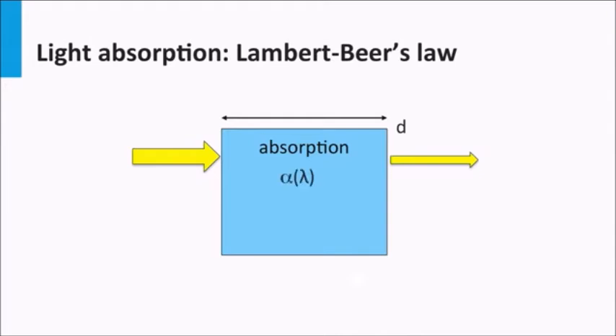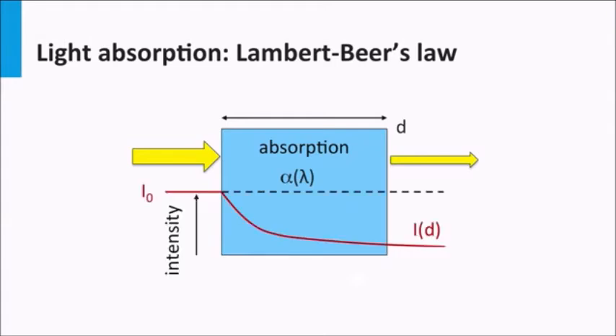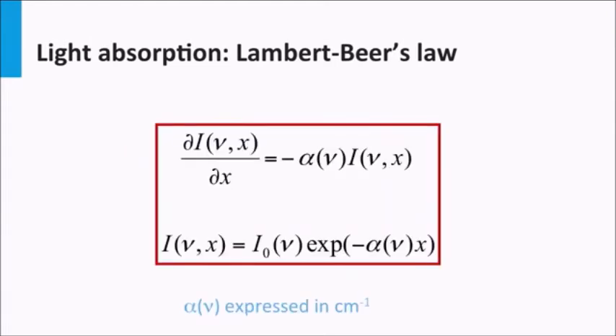The absorption of a medium can be defined in terms of an absorption coefficient alpha. The dimension of the absorption coefficient is 1 over length, and the typical unit used is 1 over centimeter. The light intensity drops exponentially with distance in the absorber layer. This behavior can be described by the Lambert-Beer law. This law states that there is a exponential dependence between the intensity of the transmitted light through the layer and the product of the absorption coefficient and the path length.